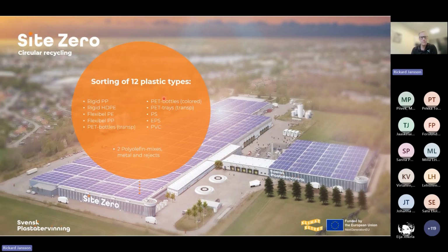After we have separated the monomaterial types of plastics, we still have a lot of packaging that weren't designed as monomaterials. So we have these laminated structures, and those laminated structures we wouldn't target for the high quality mono fractions, since they would reduce the value of these fractions. So instead we have decided to separate them out as separate plastic mixes, and we call them polyolefin mixes, and that is that typically at least one layer of these structures are either polyethylene or polypropylene based. So what we have decided to do is that we target anything that contains polyethylene or polypropylene to a certain extent, and then we are very aggressive in the sorting. So we accept that it contains polyamide or PET as separate layers in these structures, to be able to still sort them.